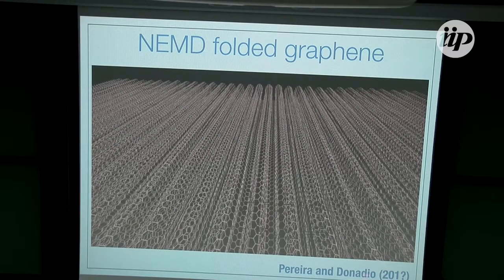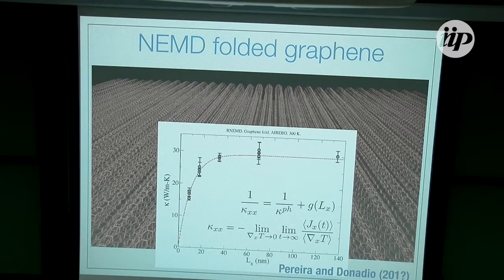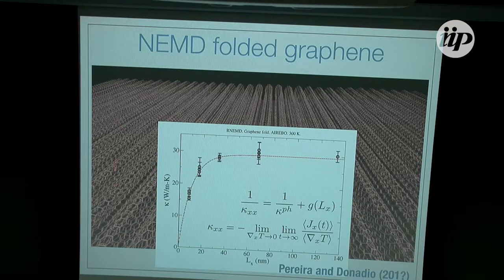This is something I did with David that we never really published. We got this graphene sheet, and we made a crest with it, right? You just compress it, and you make this crest, and then you can replicate this. And we calculate the thermal conductivity of this thing with non-equilibrium MD. I heat it up here, and I cool it down here. And we see the thermal conductivity as a function of the length of this thing. It does converge to a finite value. There's no weird behavior here.